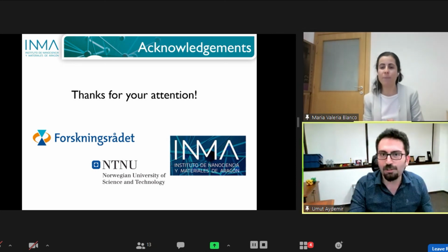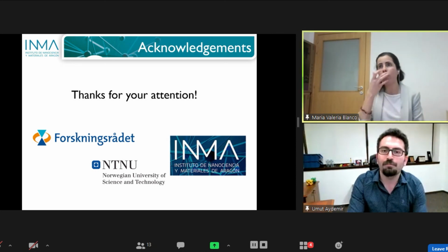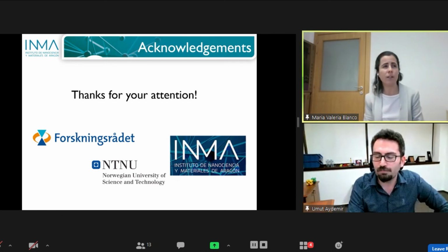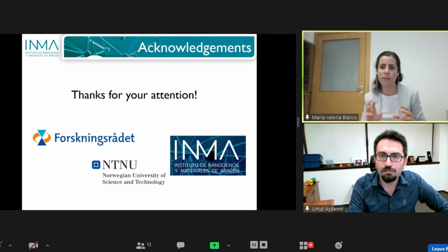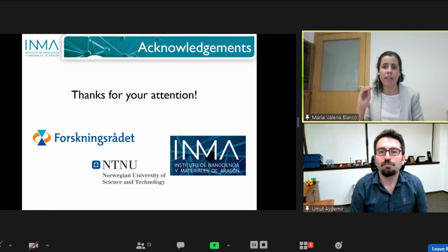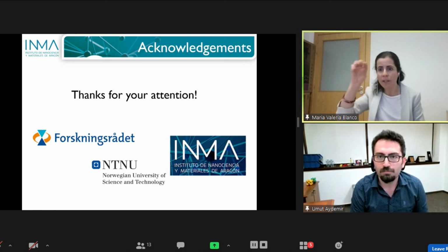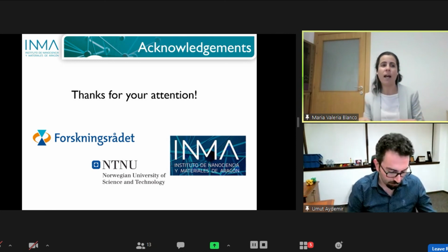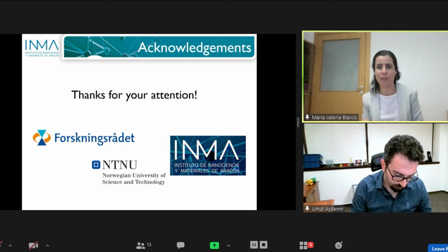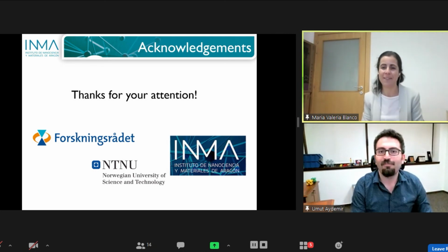Okay, so a thin layer. Commercially, I know that, for example, Panasonic is using some SiOx compounds. So it's not either silica or silicon, but some intermediate compounds, and they are mixing it with graphite. So they have, in total, up to 8% of this silicon-based material in the graphite structure. And still, you have problems with the volume expansion. Yes, so it's quite a problem, really.